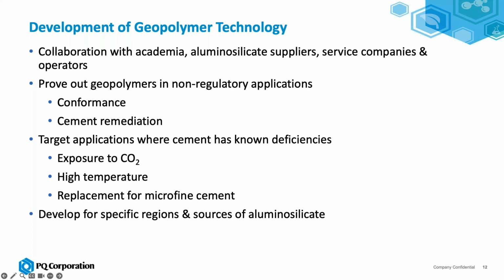And the target areas are where the material properties of Portland cement are known to be deficient. So these would be areas where there's high levels of CO2, high temperature, so thermal degradation. And then from a cost point of view, if you look at microfine cement, it's difficult to work with, and depending on the fineness of the microfine, it'd be like 5 to 10 X more expensive than Portland cement. So at those price points, geopolymers or alkali activated materials look very, very attractive in comparison to, say, a microfine cement.